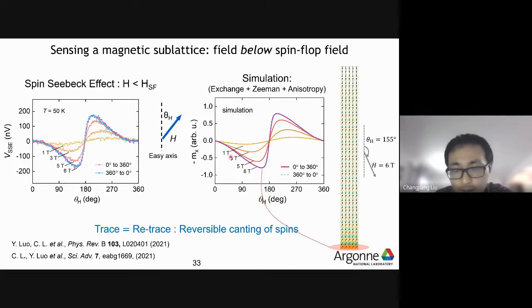We found that this response can be simulated very nicely using a micromagnetic simulation. We found that this shape corresponds exactly to the response of the horizontal component of the sublattices at the bottom surface of the chromium-2-3 as a function of the rotation of the magnetic field. So by doing this simulation, we found that this specific response, this voltage, directly measures the sublattice magnetic moment in this chromium-2-3. Here we are measuring the bottom surface because we are measuring the platinum at the bottom of the chromium-2-3.